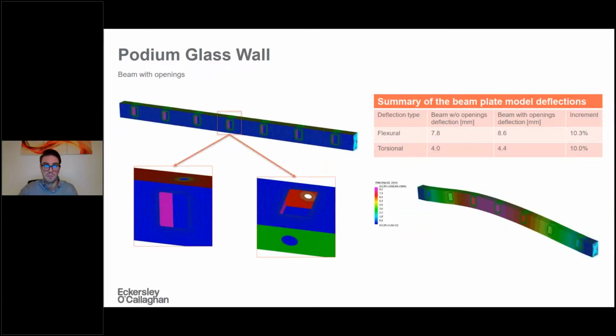And also something very important that then informed the global model was understanding the effect of the several openings that we have on the top and bottom beam, because clearly the rod needs to penetrate the beam to be anchored, and at the same time we have other openings on the side and at the bottom to either access or ensure we have space for pre-stressing the rods.